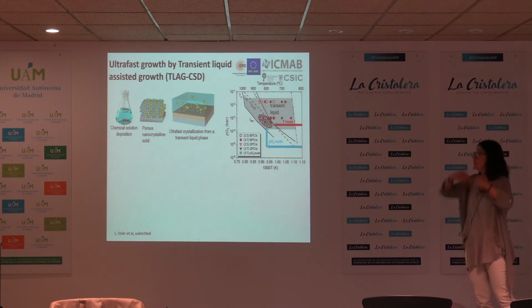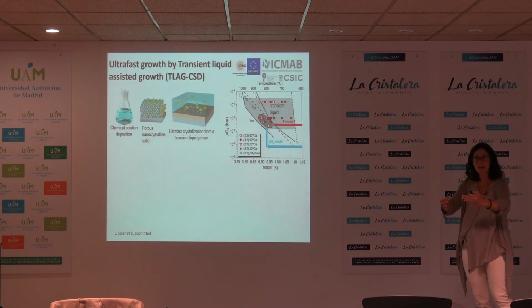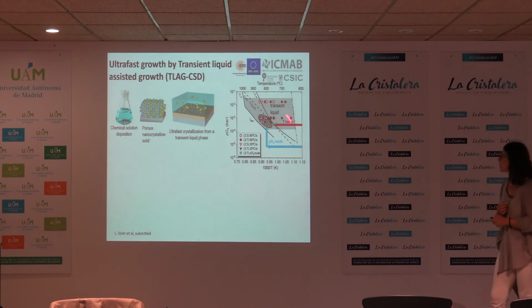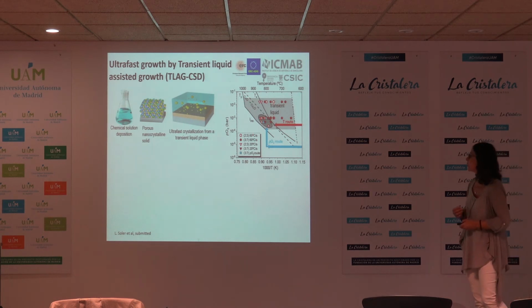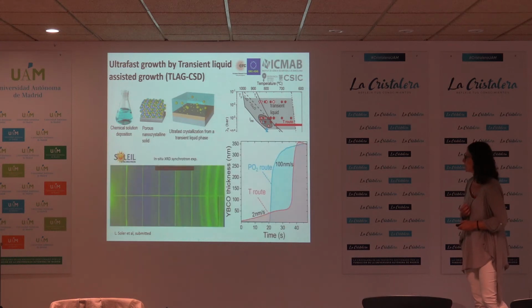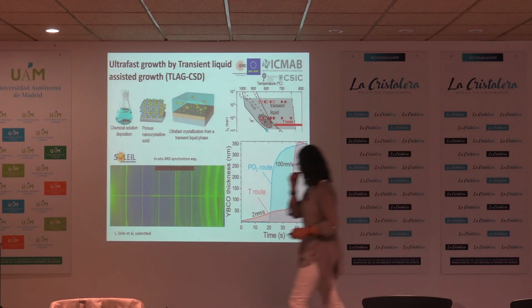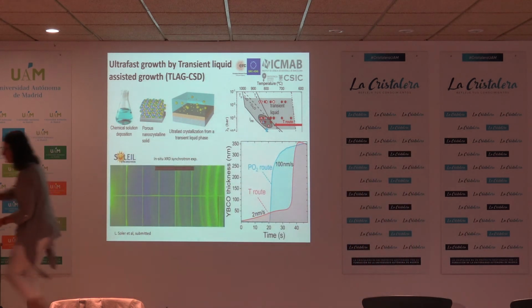And then, when this liquid is formed, the yttrium oxide nanoparticles will diffuse in the liquid and will be able to grow. That's why we call it transient liquid, because this transient liquid phase is not the stable equilibrium phase in this diagram. But we are able to produce it if we go at very fast heating rates. And we have been able to demonstrate this in the synchrotron.